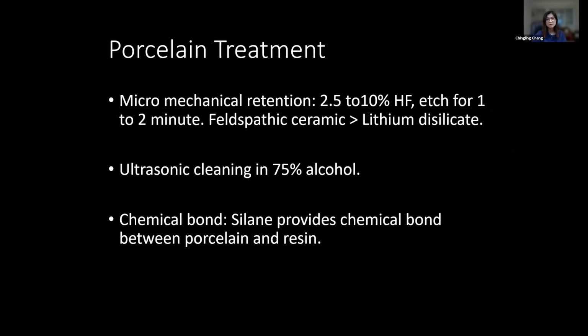For the porcelain treatment, before we deliver the porcelain restoration, we have to use hydrofluoric acid to etch the porcelain surface. It really depends on what kind of ceramic you're using. You have to read the instructions. And then after that, you clean out the hydrofluoric acid. You clean the restoration in 75% alcohol in an ultrasonic cleaning machine to remove the fragile particles that come out from the etching. And then you apply the silane on the porcelain surface to provide a chemical bond between porcelain and resin.